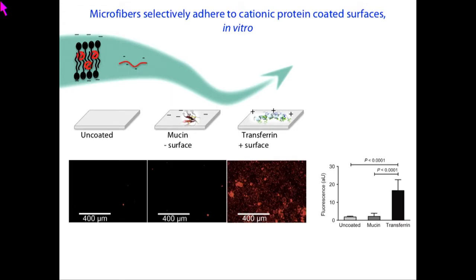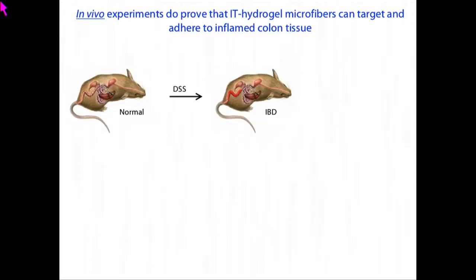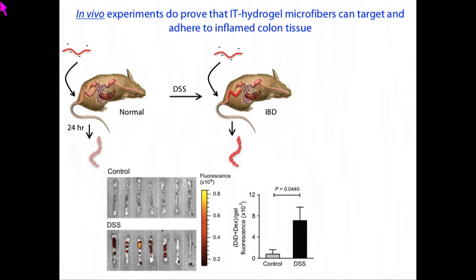We selected small molecule amphiphiles that can self-assemble and encapsulate the drug — in this case mesalamine for colitis. In addition to self-assembly, the particles should carry a partially negative surface charge, and should also have the ability to release drug in response to enzymes. We extensively characterized the nanofibers, showing they are highly negatively charged and inflammation-responsive. In animal studies, inflamed colon showed high amounts of fibers attached even despite large bowel movement, whereas in normal colon, traces of signal were essentially absent — suggesting the material adheres specifically to the site of inflammation.